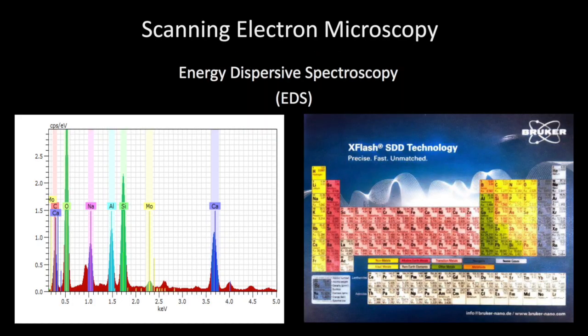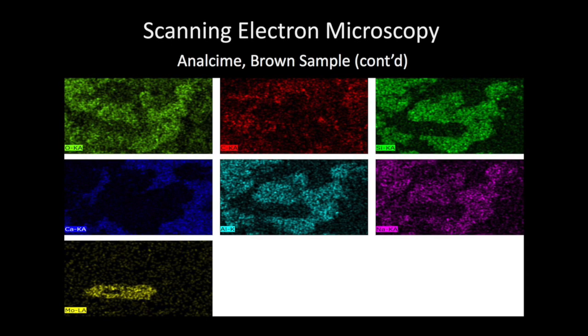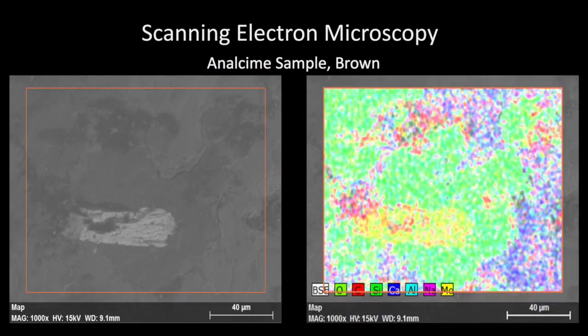This graph is the energy dispersive X-ray spectroscopy, or EDS. Similar to X-ray diffraction, this uses the spectral line of the element itself. The bottom X-axis is your energy readout from the spectral line, and each number is a signal corresponding to the actual element it belongs to. In the results you have your sodium, aluminum, silicon as dominant elements, and your oxygen. You also have calcium and carbon in your oxygen, which is your calcite. But it's just that one part of molybdenum that's just sitting there. This picture shows the distribution of all these elements and their concentrations.